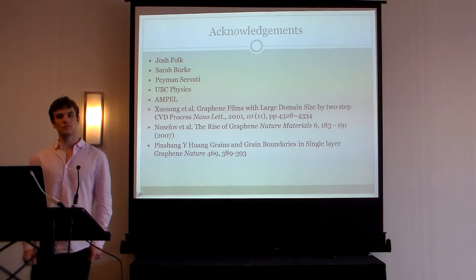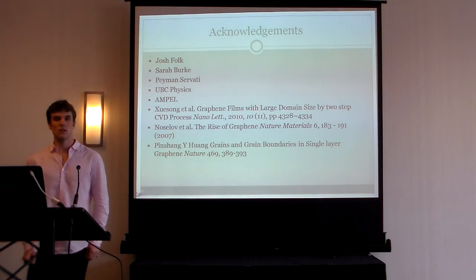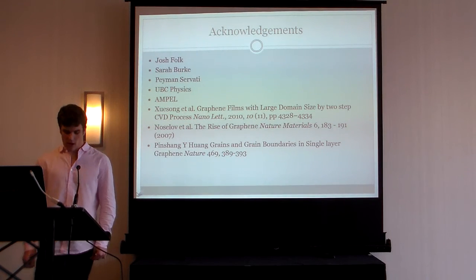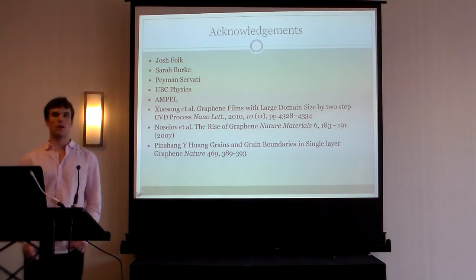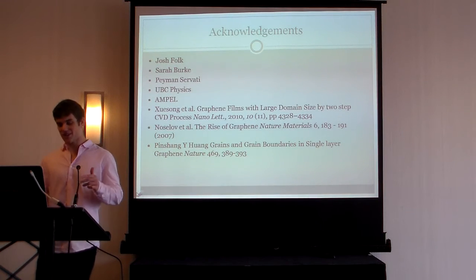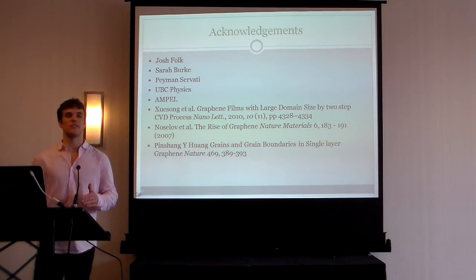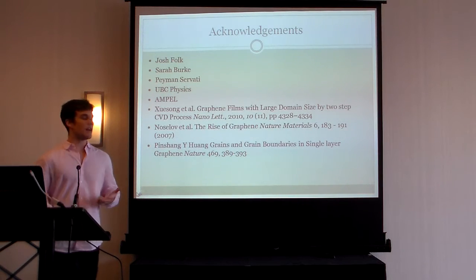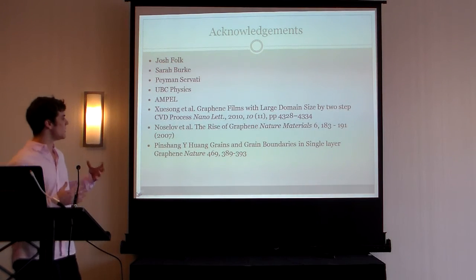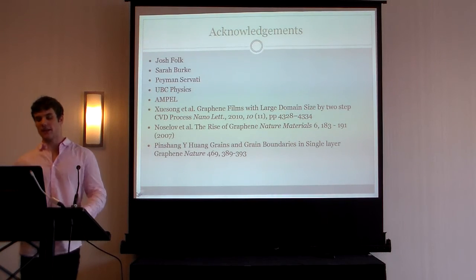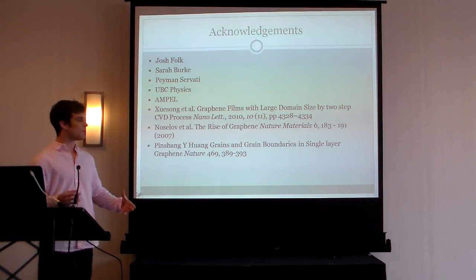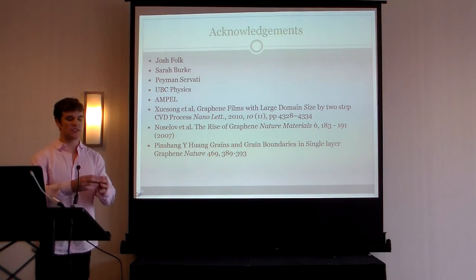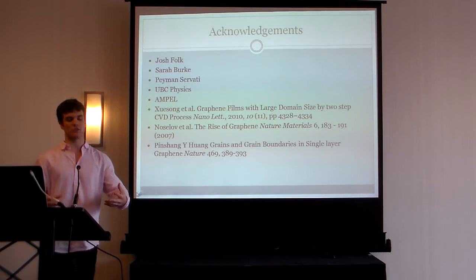What ratio of gases did you use for this, and do different ratios of gases build different structures, or do you have more defects depending on your ratios? I've actually done quite a bit of testing, and there's quite a lot of literature about the ratio of hydrogen to methane, and what that really causes is the change between an equilibrium and a kinetic reaction. When you have a lot more methane than hydrogen, you get these large dendritic non-hexagonal structures.